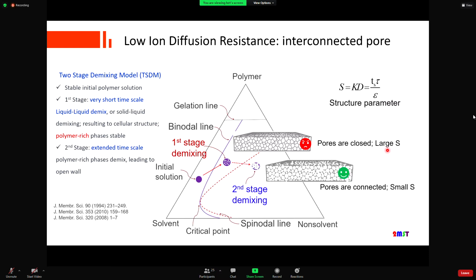But at this stage, if your polymer rich phase has two immiscible polymer pairs, they will start to demix. This is the second stage demixing, which will break up the polymer rich phase to give you an interconnected pore. There we will largely reduce the structure parameter.